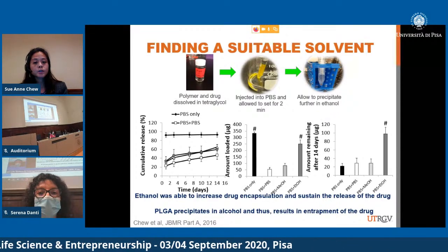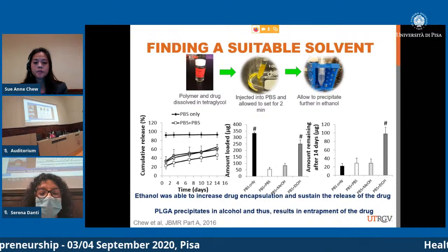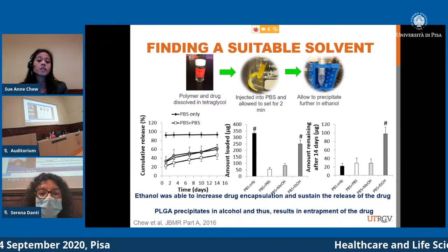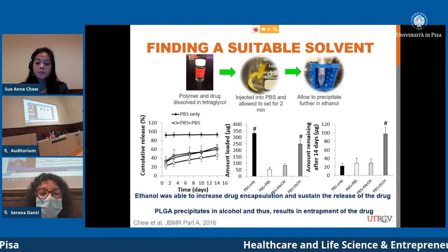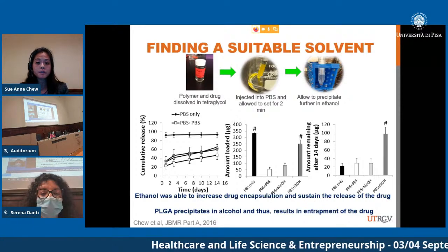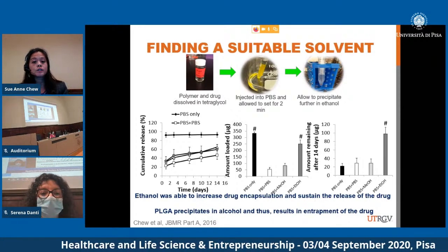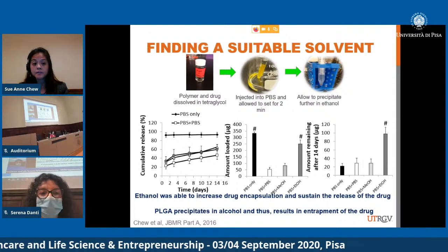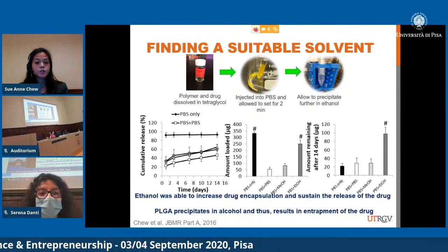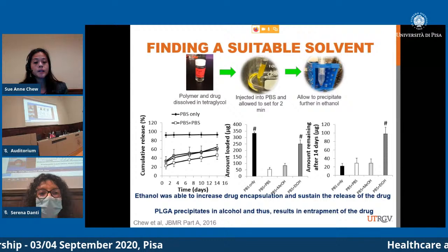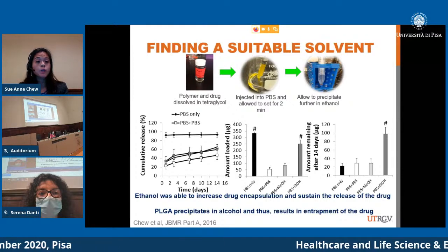So, after we inject the scaffold into the PBS solution, it will precipitate. So the tetraglycol will come out of the solution into the PBS, and then we moved it into a different solution to further precipitate it. So, we tried different things. We tried PBS, we tried methanol, we tried ethanol.